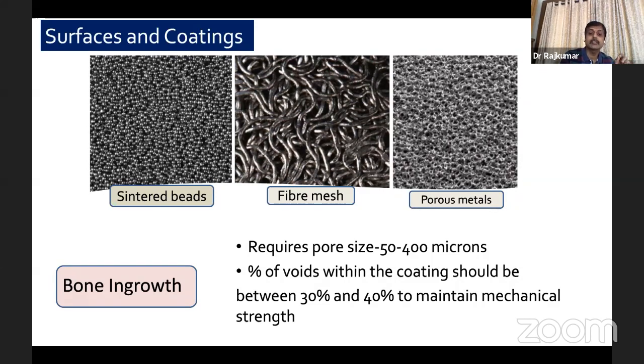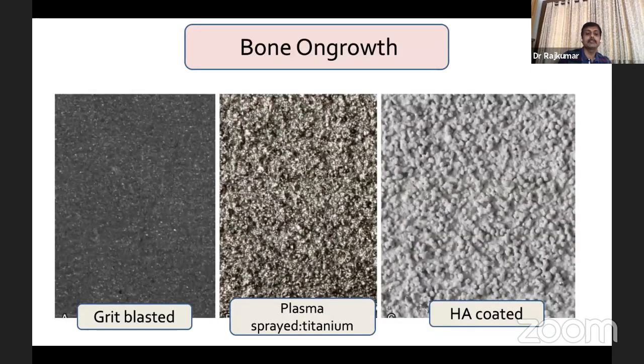The percentage of voids, that is the porosity, within the coating should be between 30 to 40% to maintain mechanical strength. So the porosity should be between 30 to 40% of the entire coating. Then the bone ingrowth is good. Bone on-growth happens in materials that are grit blasted, plasma sprayed titanium, and HA coated, like all your Corails and Wagners. The bone grows over the implant, whereas in a stem like an Accolade or a Summit, the bone grows into the